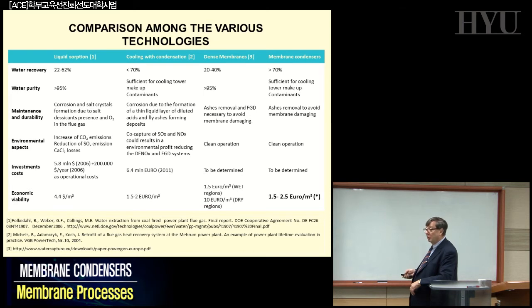If you are just working on water in your gas stream, no big problem. This membrane can be stable, the dense membranes. If you start to work, not in real life, when there is sodium, hydrogen sulfide or hydrofluoric acid, as we have in some cases, etc., you must be careful because some of the membrane polymers you are using, in this case PEBAX or some polyamide, etc., can have trouble in the long term. These polymers are expected to have this problem. Remember that